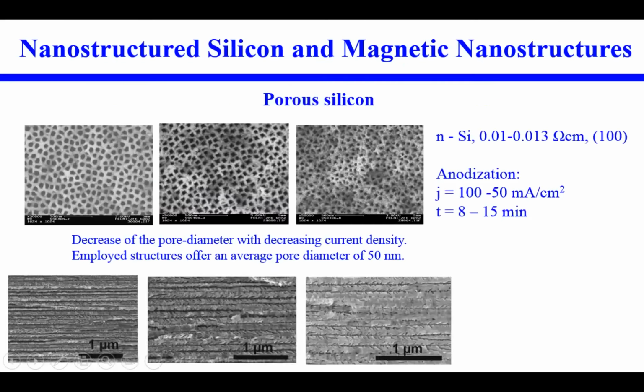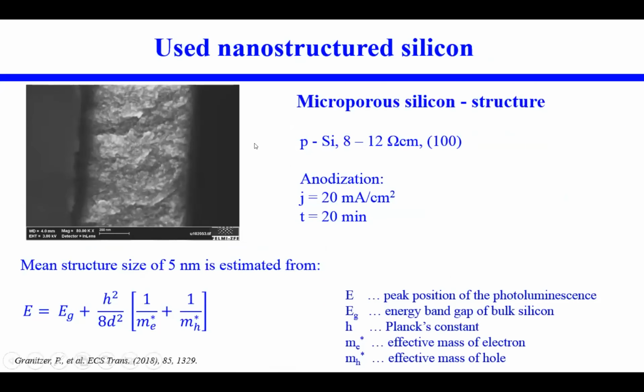So these are typical porous silicon structures we are using. Here the diameter is between 50 and 25 nanometers, and it's produced from a highly doped silicon wafer. And you can see that with decreasing pore diameter, also the regularity of the pore arrangement decreases and the dendritic growth increases. And for magnetic investigations, it's beneficial to use quite regularly arranged pores, and so mainly we use porous structures with average pore diameters of 50 nanometers. So this is a microporous silicon structure produced from moderately p-doped silicon, and it offers a structure size of about 5 nanometers, which is estimated from photoluminescence measurements.